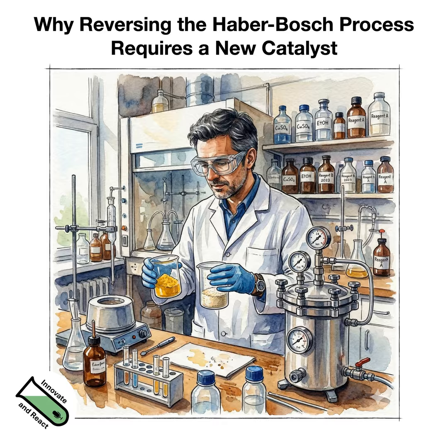We're not doing process optimization or anything. It's all on the catalyst, but it is also important how the catalyst formulation is synthesized in order to compare catalysts. It's not iron equals iron. I can make a very bad and a very good iron catalyst. I can do the same with ruthenium. And unfortunately, it's very easy to make it bad. To have this high porosity with a high exposed metal surface area is sometimes challenging, and it has a lot to do with inorganic solid state chemistry. So I come back to what I said in the beginning. Those are some aspects that are needed in order to stabilize these porous sponge-like structures that we aim at.